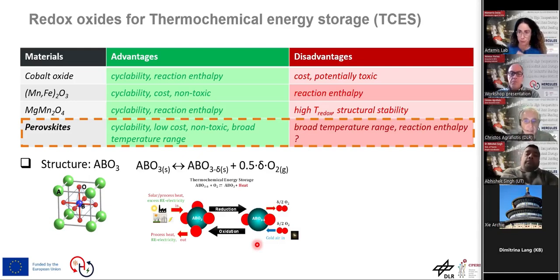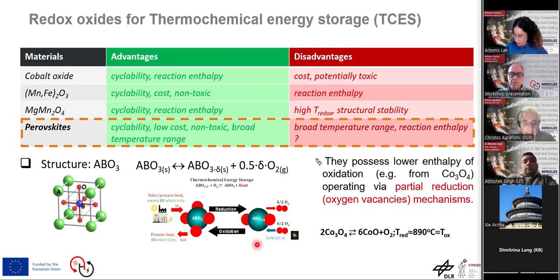And as a consequence, if we click, we will see that the heat effects of these reactions are less than for cobalt oxide, which operates via a full structural transformation scheme, as you see in this reaction where Co3O4 goes all the way to CoO, and the amount of heat is higher. So in general, exactly because the perovskites operate with partial reduction, otherwise called oxygen vacancy mechanisms, that's what explains the lower reaction enthalpy effects that we see on top.